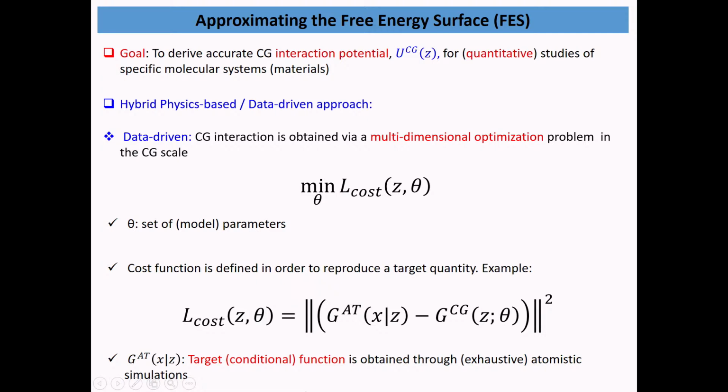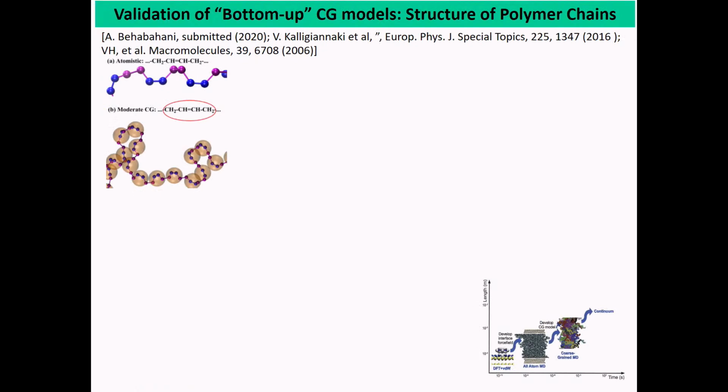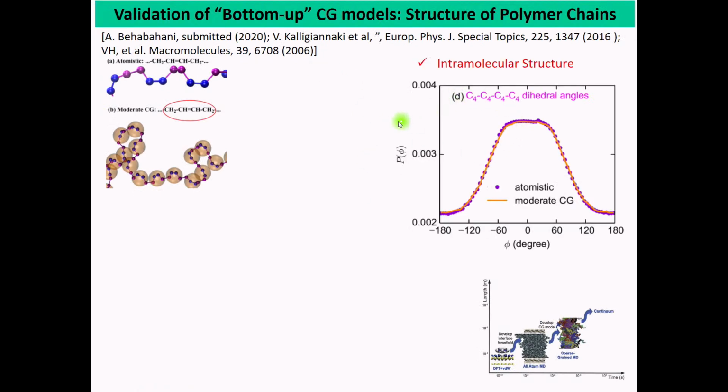So typically, as you know even better than me as a physicist, everything in nature is energy, right? Energy and derivative of energy, which are forces. So practically here we use energies and forces. That's the most standard one. But we can use also structural quantities like this. And the reason is why? Because these are actually derived via Boltzmann distribution, so these follow e to the minus beta U. So if you match the probability distribution function of structure, you match more or less the underlying free energy in the system. All these are at the free energy level, because we have actual temperature.